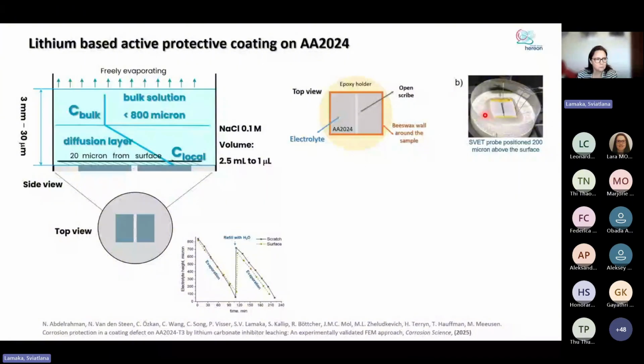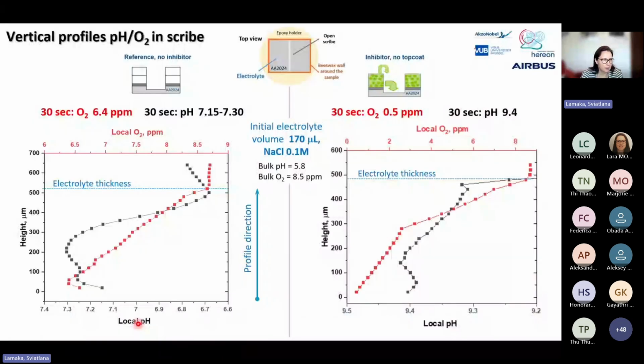So these are the first results. In this case, these are vertical profiles of oxygen and local pH recorded with microprobes, either for the reference sample or for the one with corrosion inhibitor. And we started measurement 30 seconds after adding electrolyte to the system, so very, very soon at the beginning of immersion. And so for the reference sample, we observed a slight depletion of oxygen compared to the bulk values of oxygen, and slight alkalinization, again, compared to the initial bulk values.